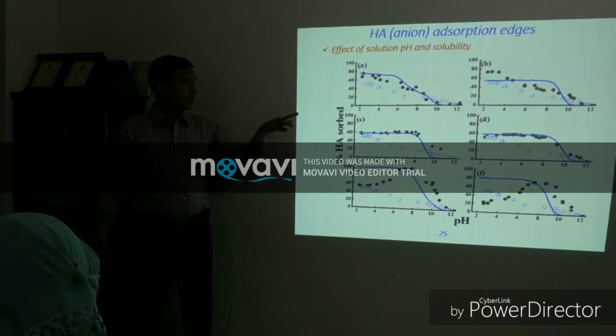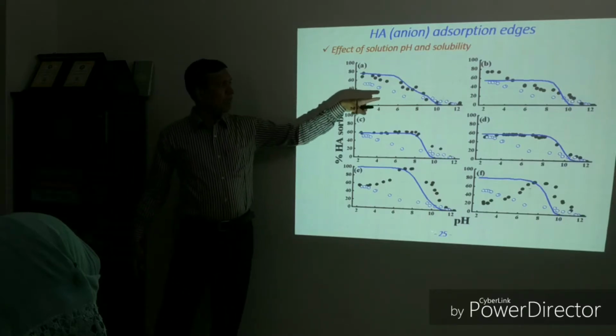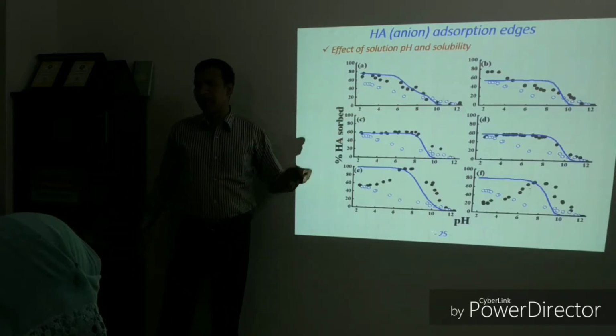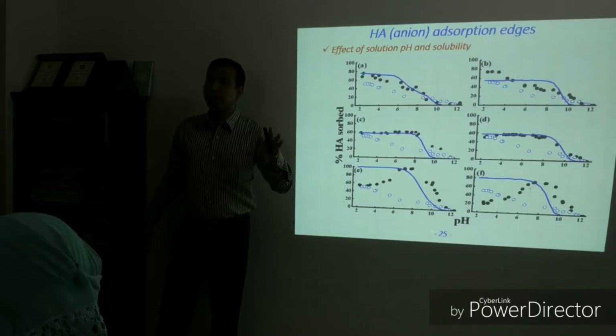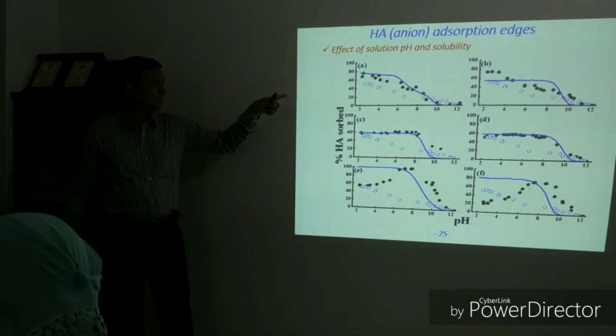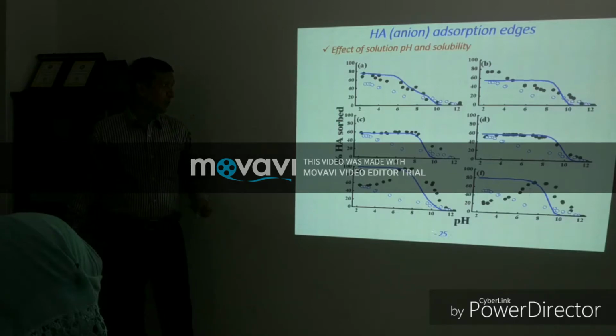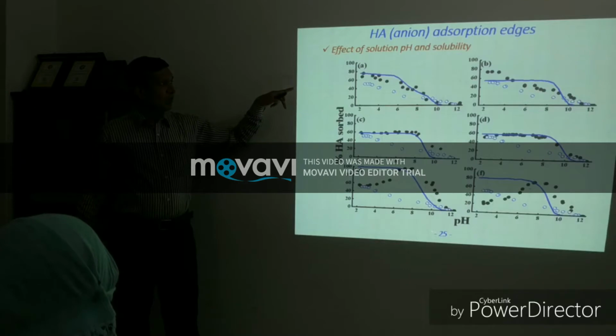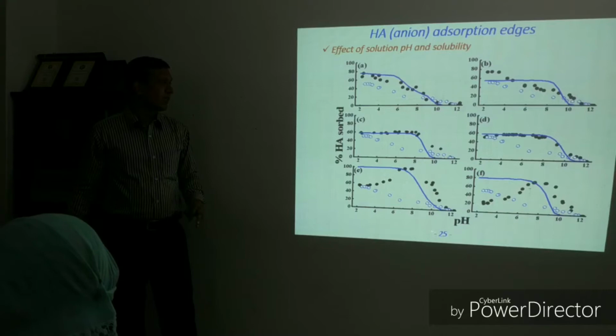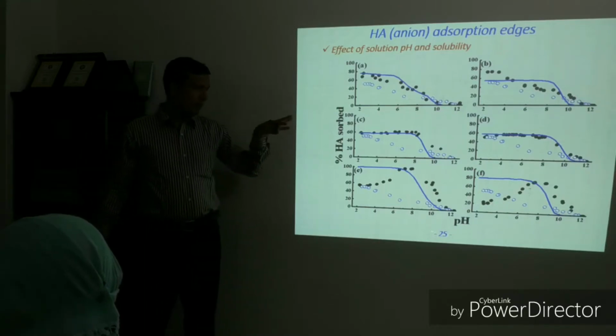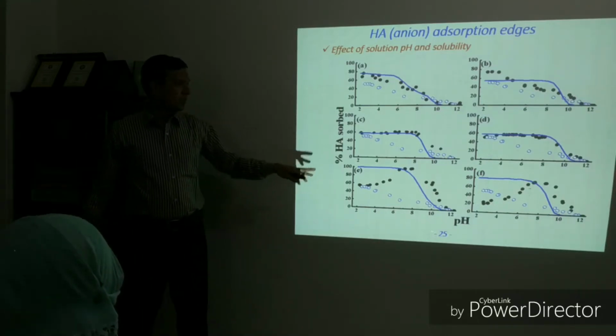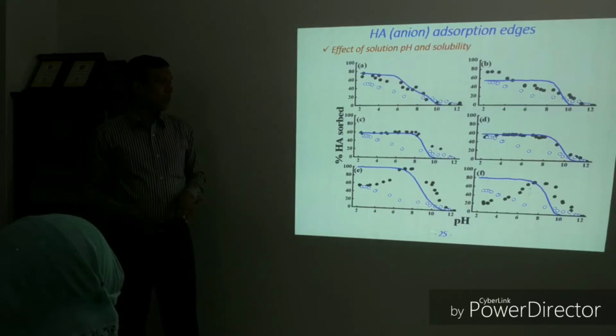Then we have studied humic acid adsorption edges. Here the dotted line indicates the solubility of humic acid, and the amount of adsorption can be estimated by the difference between solubility and adsorption. So again we see that in the case of birnessite, adsorption decreased with increasing pH, and due to different surface properties, different shapes of adsorption edges occur.